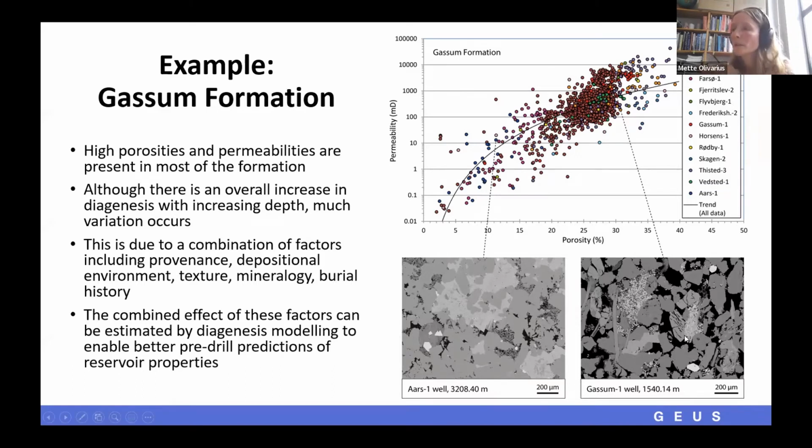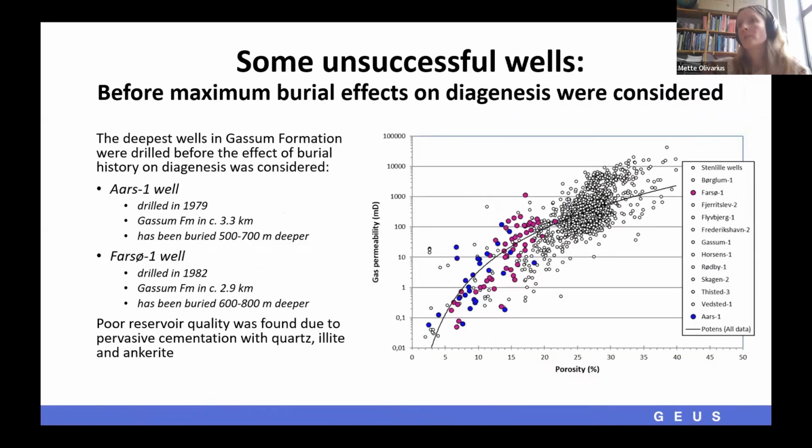So to the right, you can see there are a lot of black areas, which are the pores between the grains. This corresponds to a high porosity and permeability, whereas from this well, there are very few and small pores left due to very enhanced diagenesis, also corresponding to a large depth here. And this is just the same data set you just saw before.